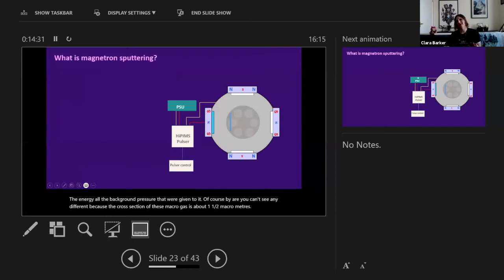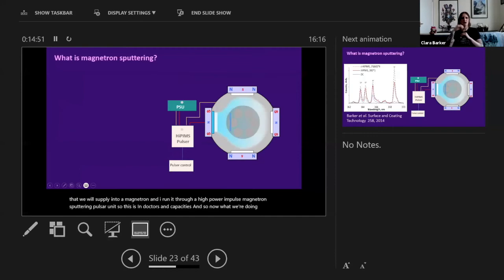And what I did for about 10 years during my PhD and postdocs was I took the voltage that we were supplying to a magnetron and ran it through a high power impulse magnetron sputtering pulser unit. So this is inductors and capacitors. Now, rather than having a DC voltage supplied to the target, we're actually pulsing it. We have hundreds of volts, but we can also have hundreds of amps at the same time. So this is very high power.